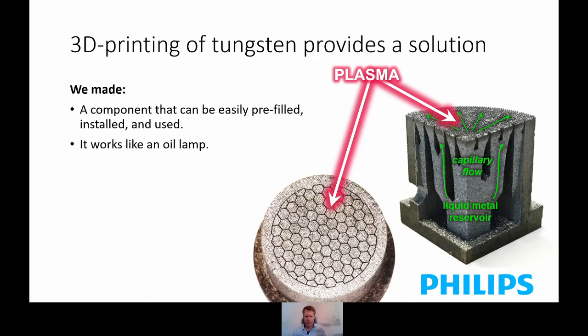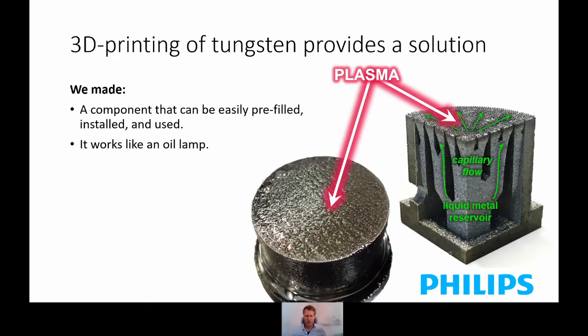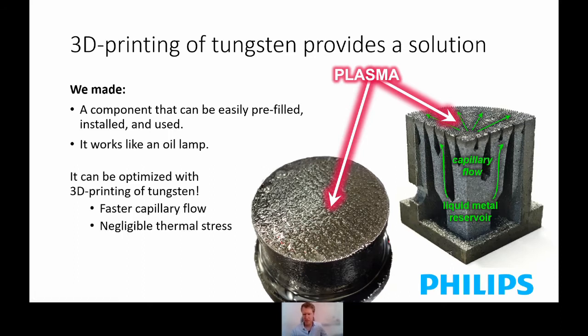So you take a bunch of these, you fill them outside of your experiment, you prepare them, then you put them inside your experiment, you use them until the liquid metal is depleted. And afterwards you fill them again, which looks beautiful, by the way. So here's a target filled with lithium in the glove box at DIFFER. So this works great. And what's even better is that because we can use 3D printing, because of course there are other ways to make solid porous materials, but with 3D printing you can really control very well the internal geometry of such a sample. So you can maximize capillary flow, and you can reduce thermal stresses due to heating, thermal expansion, bending. You can reduce those stresses to virtually negligible levels.